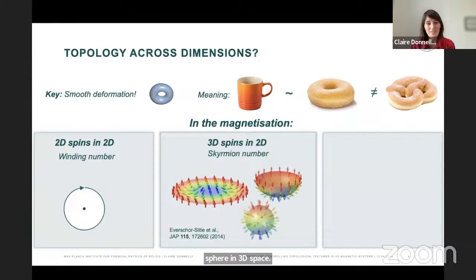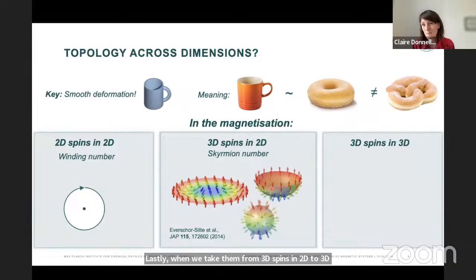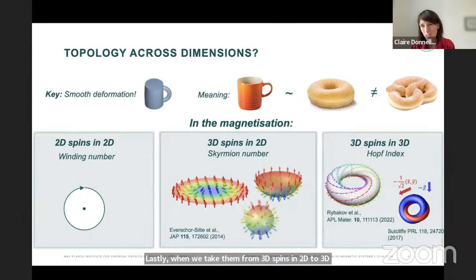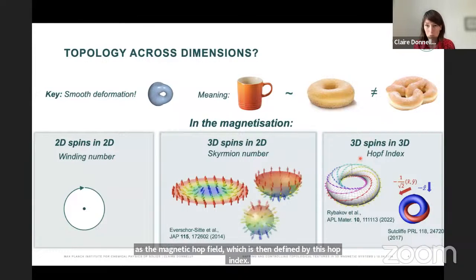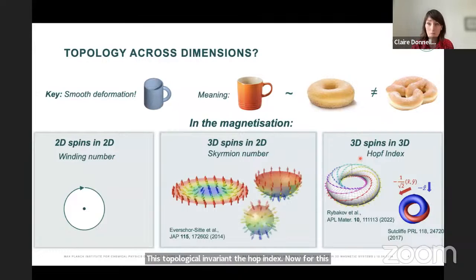Lastly, when we go from 3D spins in 2D to 3D spins in 3D, we then get something which is known as the magnetic Hopfion, which is defined by this Hopf index, this topological invariant. Now for this, what we really need to emphasize is that for Hopfions to exist, we really need the combination of a three-dimensional spin texture and our three-dimensional space. And these in principle can form these kind of soliton-like textures in our materials.